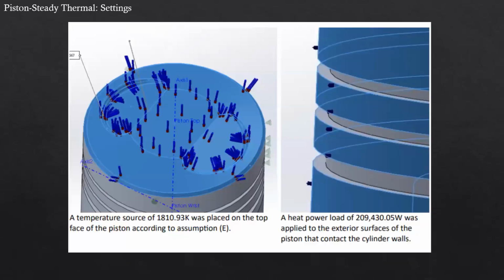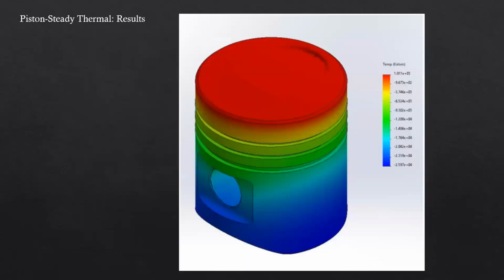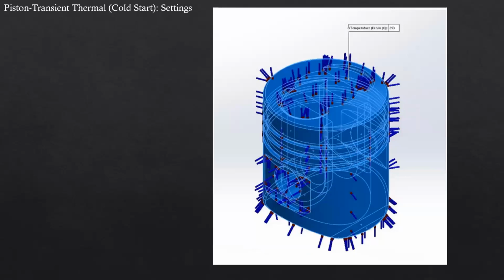Moving on to the steady thermal analysis of the piston, we put in a temperature source of 1810.93 kelvins at the top face. And then we had a heat power load of 209,430.05 watts to the exterior surfaces. And then the results are presented here. We're not dealing with significant stresses from the heat application, and it's actually cooling relatively well going through the body of the material.